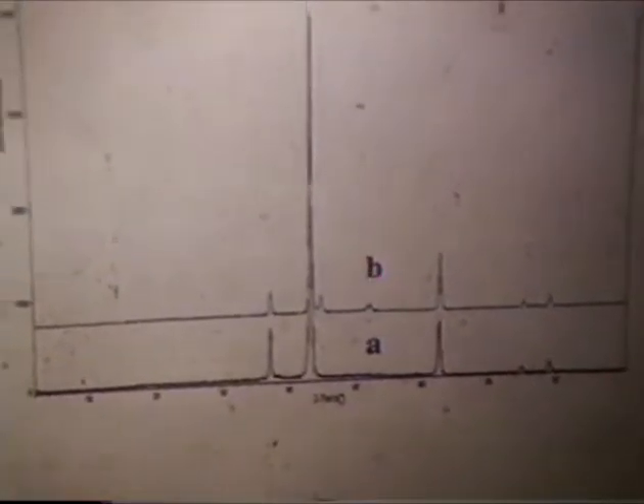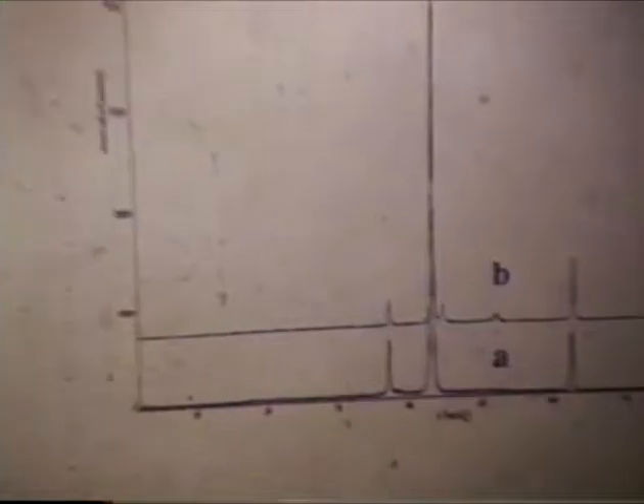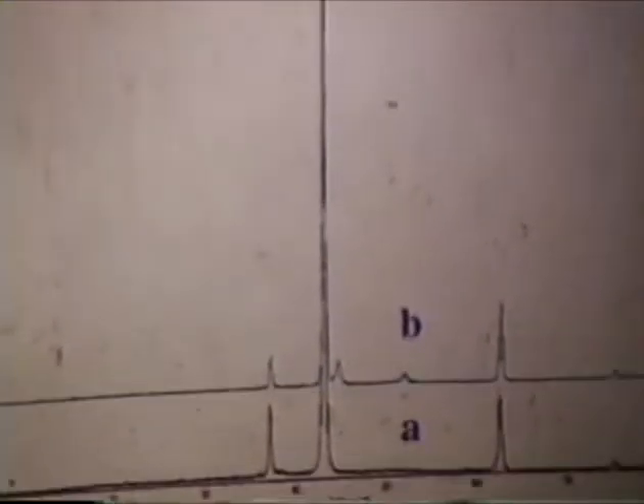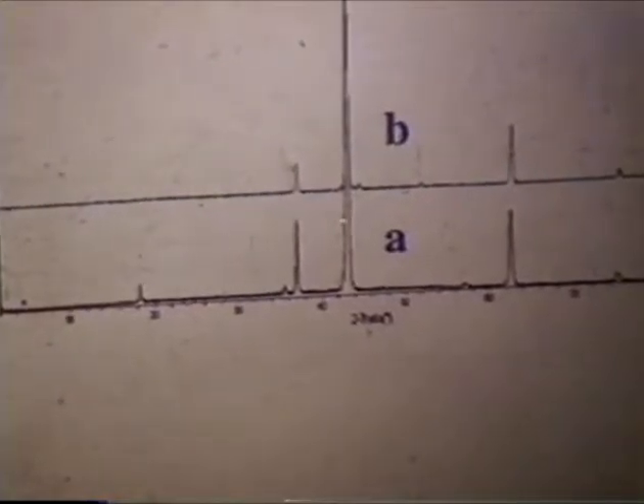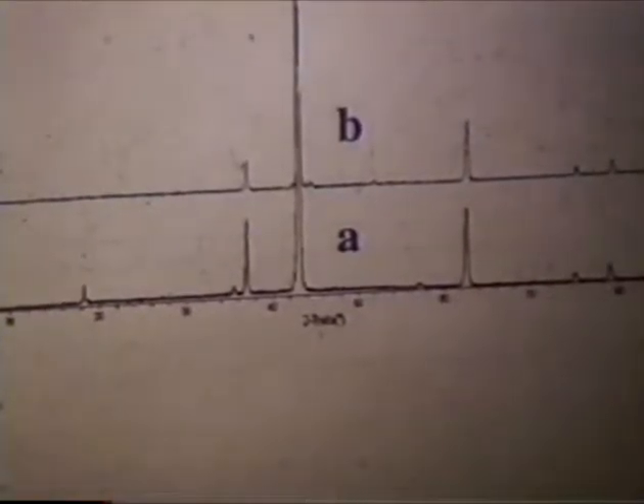We also did an XRD analysis of the unpromoted catalyst. This is unpromoted, and you can see fresh being A versus used being B. You're seeing some of the nickel metal phase grow in. So with use, you are reducing the nickel plus 2 to nickel 0, which is not what you want. Whereas with the promoted catalyst, with the manganese now shown here, your fresh and your spent look very similar. You can see maybe a hint of the nickel metal pattern coming in. Again, though, we could not quantify the coke with TGA.